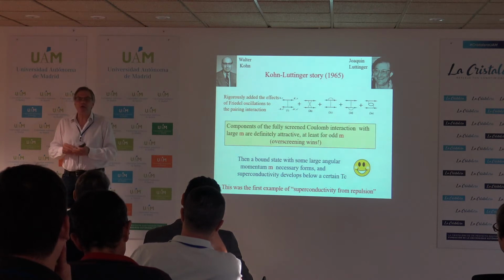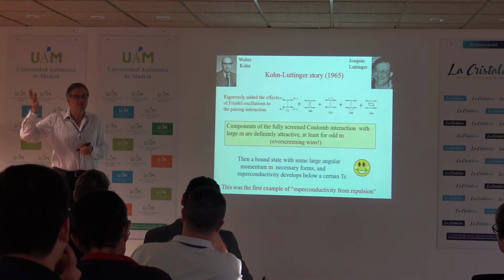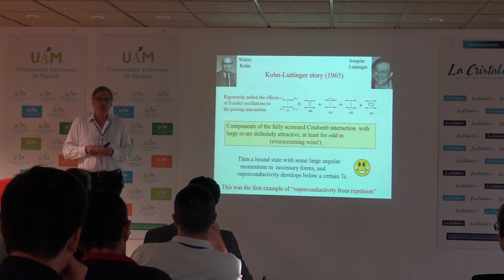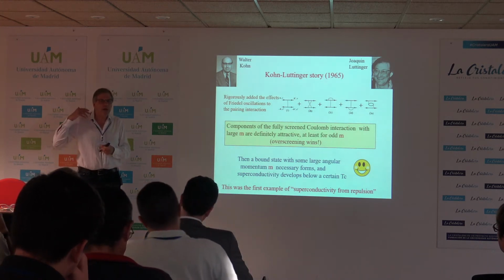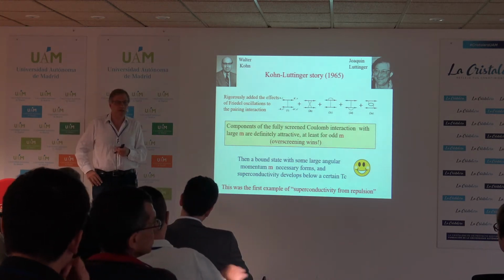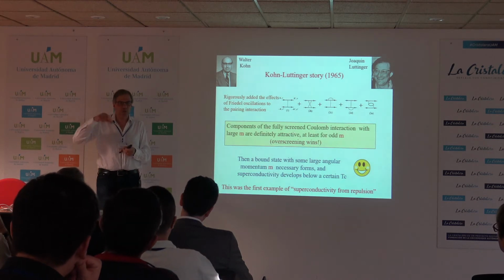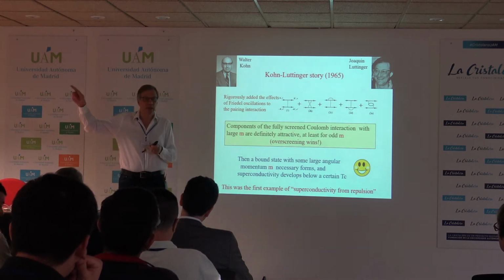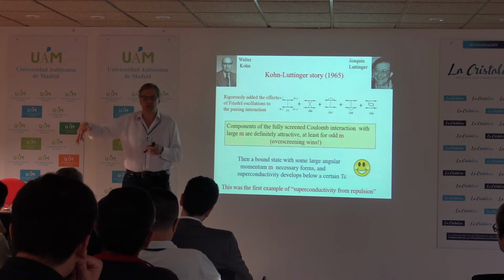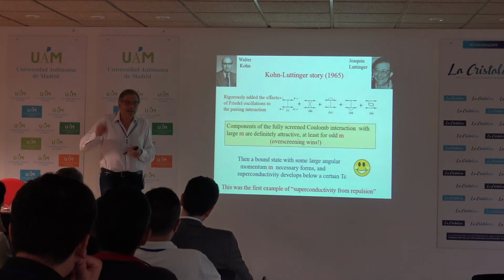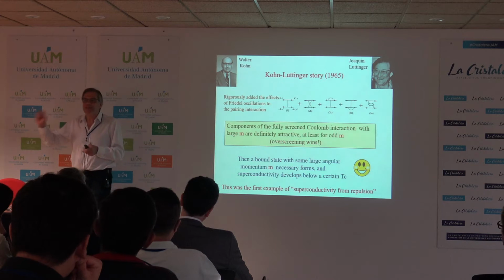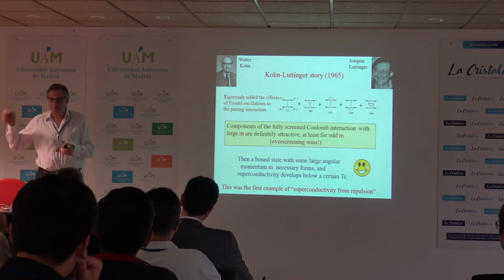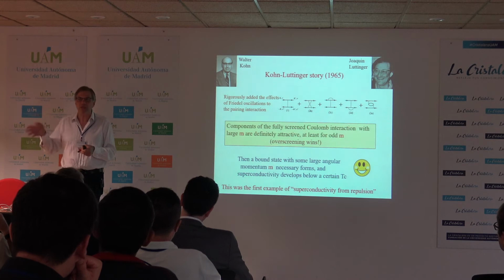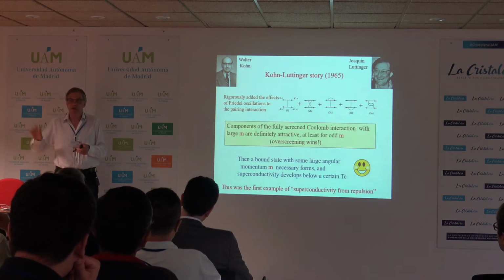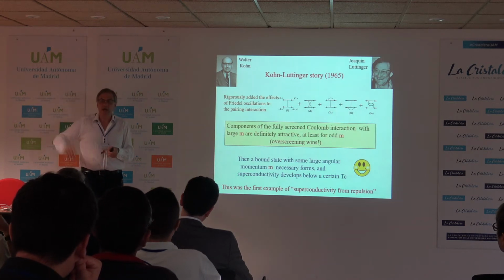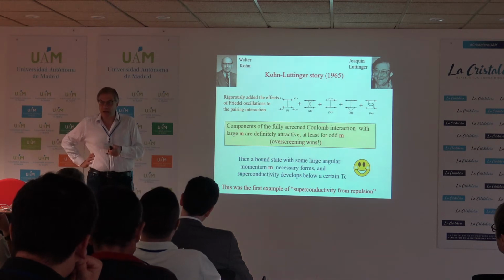Because if you take regular screened interaction, some analytic function u of q, and calculate what will be the partial component with large angular momentum m, you get a partial component which is exponent e to minus m. So for large m, it's exponentially small. Friedel oscillations give you non-analyticity in the function u of q. It's logarithmic non-analyticity, but still non-analyticity. That's a term which in Fourier transform gives you cosine 2k r divided by r cubed.